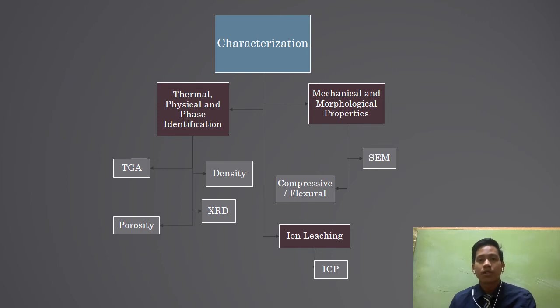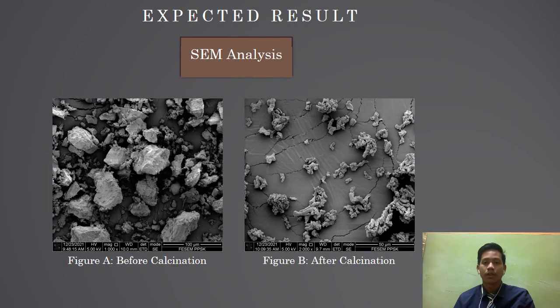XRD will be used to identify any unknown crystalline phases resulting from variation of sintering temperatures. Physical characteristics such as density and porosity are deemed crucial as they will affect the efficacy of the filtration system. Meanwhile, TGA will be used to observe the effect of sintering temperature on thermal stability of the composites. Finally, the assessment of ion leaching will be performed using an inductively coupled plasma machine. Now, let's move on to the expected results.